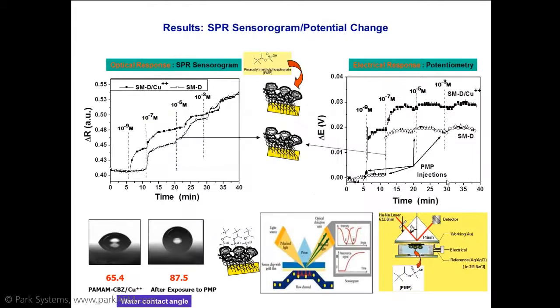So for example, in terms of efficacy, the initial experiments we did were to look at the reflectivity response as a function of concentration. So SPR sensorgrams show that we can detect up to 10 to the -9 molar, or nanomolar sensitivity. That is, with the copper-containing material, we get to the limit of 10 to the -9 molar. However, without the copper, it only reaches up to 10 to the -7 molar. So clearly, the presence of copper enhances the sensitivity or detection limit for the analyte.